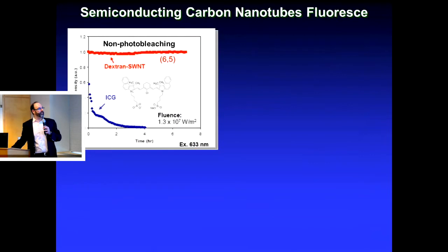this fluorescence has very interesting properties. First, it's completely non-photobleaching. So many of you in the audience, if you have a biological background, you have used fluorescent dyes for staining. Most organic fluorophores will photobleach. Carbon nanotubes have no photobleaching threshold. This is indocyanine green. It's a near-infrared fluorophore that's used. It's actually FDA approved for biomedical imaging. But see, it photobleaches readily without too much light. Under the same conditions, you'll get a pretty steady fluorescent signal.